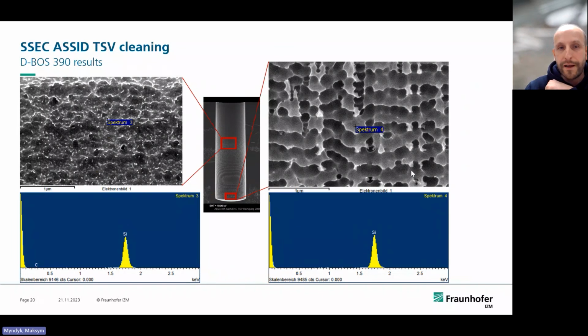But to be definitely sure that the material performs as it needs to perform, we did the EDX analysis in the middle of the TSVs and on the bottom. And what we see is that no carbon-fluor bonds, reflex, or signals were found in this particular case.